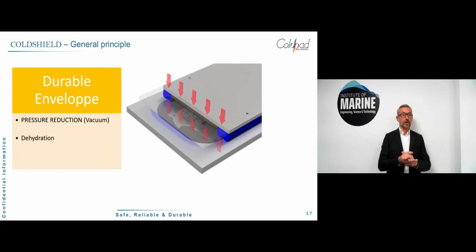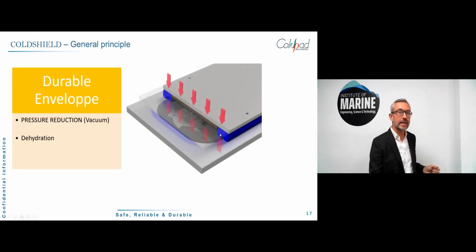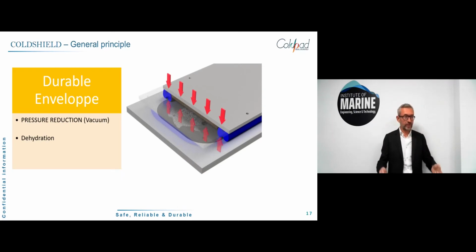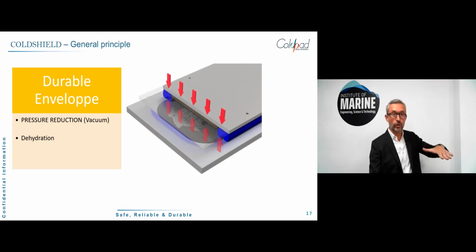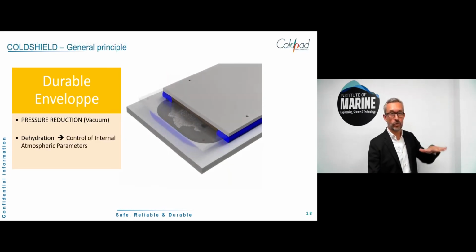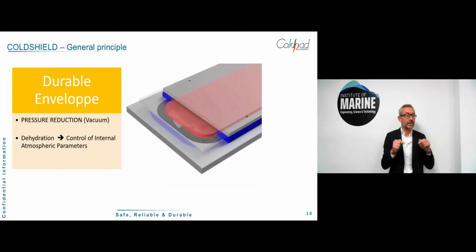So this thing will be prefabricated, so the seal and the super duplex plate and the intermediate layer will be prefabricated. They'll arrive in a blister, okay, and then we'll take off the plates, we do the surface preparation, and then we set this reinforcement onto the base metal. And then what we do, we apply a pressure reduction, a vacuum, that will act like a vacuum cup, okay? So we have a vacuum cup, and then we can isolate the internal volume from the external environment. And this is where we control the atmospheric parameters. And this is where we apply a dehydration in order to reach a very low humidity level. When I say very low, it's less than 10%.